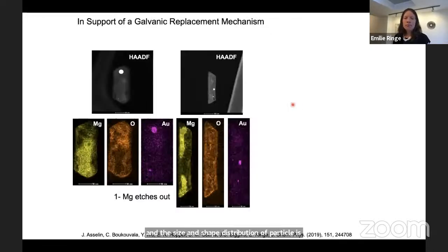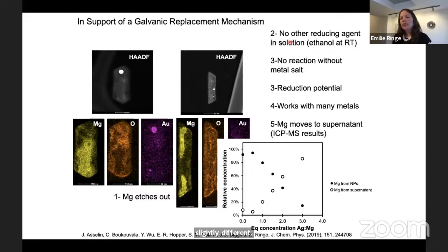We're pretty sure this is a galvanic replacement mechanism by now, because we do see the magnesium etching out. We also are convinced that there's no other reducing agent in solution. The gold doesn't get reduced by anything else.